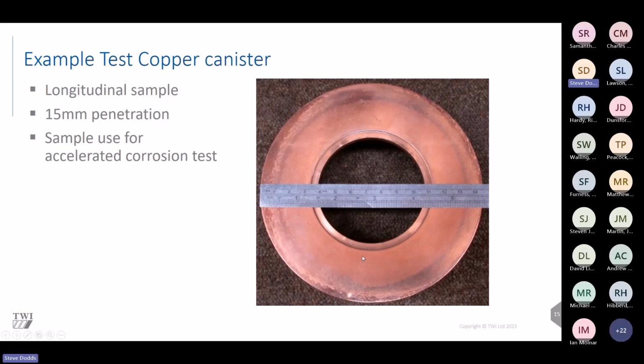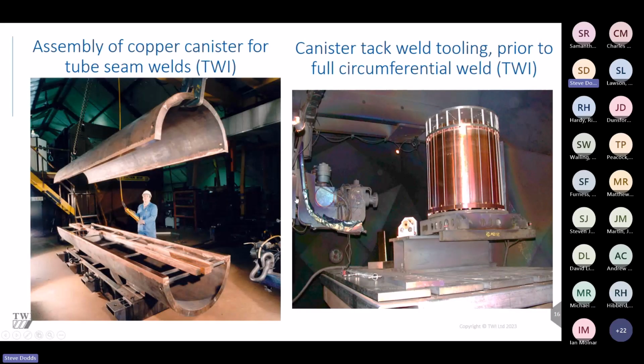Here's a section of copper canister. So you can see here a 15mm penetration, partial penetration, and that was then used for the corrosion testing that we did as well. And then finally, some big pictures again of the copper canisters, either seam welding the bent copper plates together to make tubes, or on the top there, this is a castellated sort of tooling system where we first tack weld in between the braces and then take off the tooling system and go for the full circumferential weld in one go.